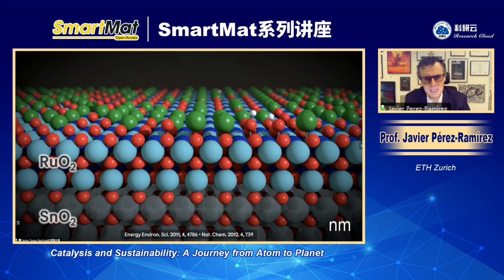Now, this catalytic material is based on a ruthenium oxide catalyst epitaxially grown on tin oxide as carrier. And this epitaxial growth, where you see two layers of ruthenium oxide, has been essential to have a very stable catalytic material displaying a high activity and also trying to economize the utilization of a very expensive noble metal like ruthenium oxide. So effectively, the optimal catalyst that is implemented in industry contains two layers of ruthenium oxide epitaxially grown